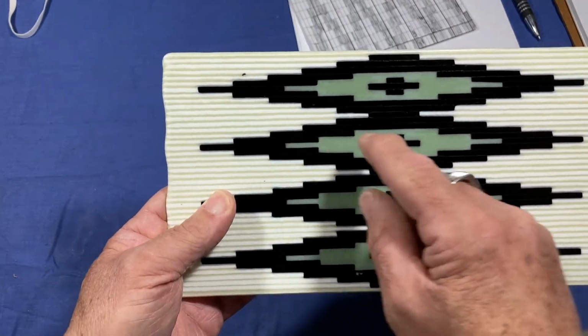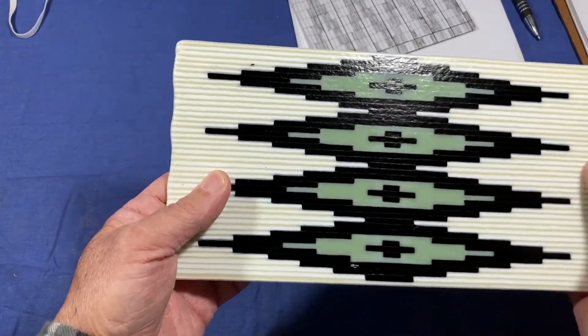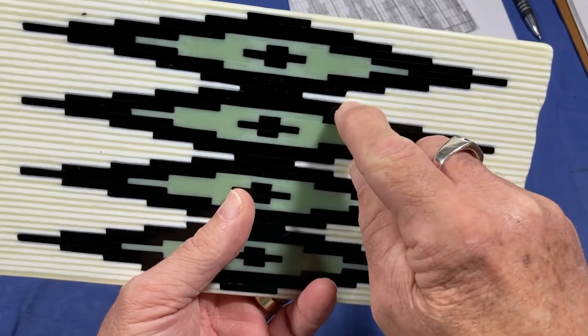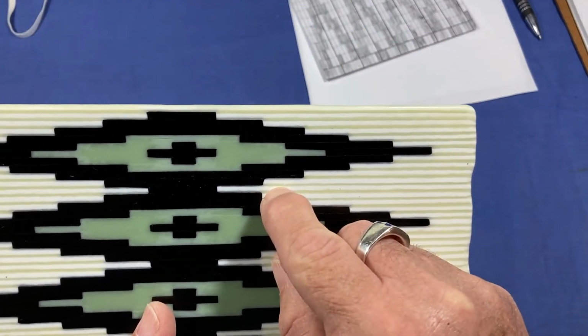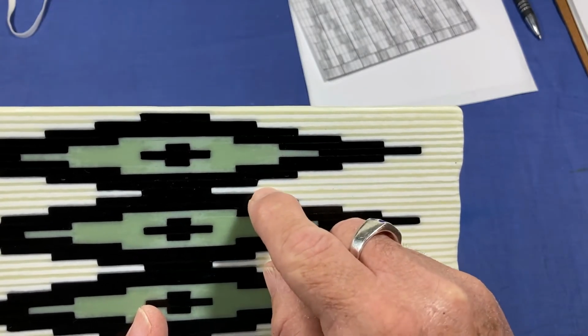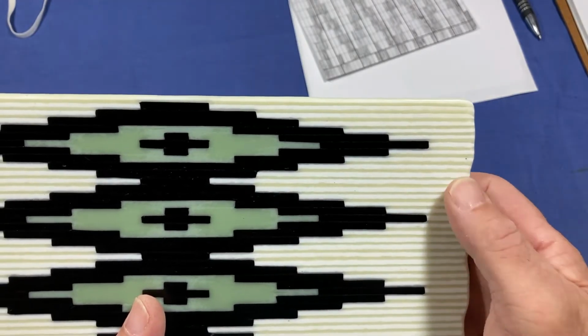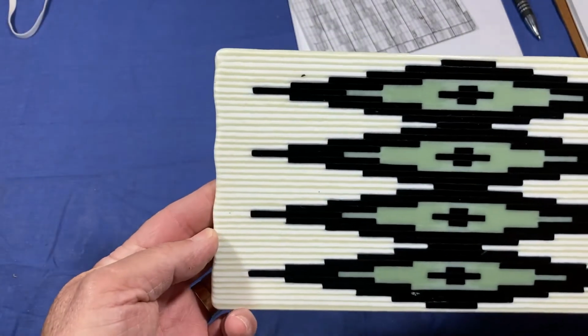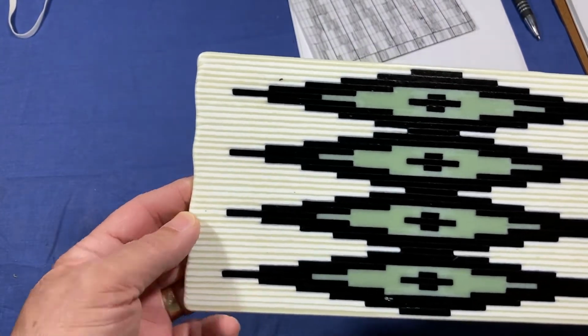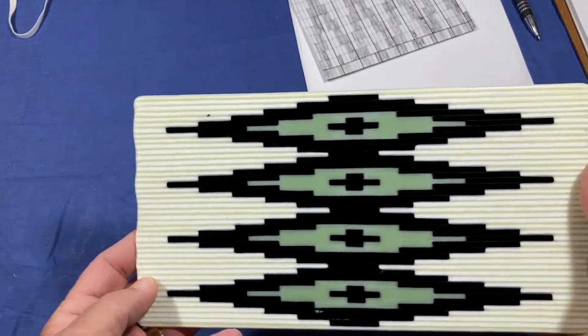That's just French vanilla. And yes, I know French vanilla, when it fuses, you do get white parts. And that's what's happened. Everywhere it's joined, you can see there, I'll move this over, where the join is, the actual solid part has gone lighter in colour, but the join has stayed much more like the vanilla. So we've got these really nice designs there. Can't say I've noticed that before, but that's probably because I haven't done large areas of vanilla just alone. It's usually interspersed with other colours.